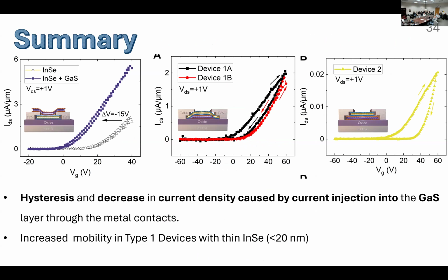So in summary, we have presented 3 different device configurations, and we have explored how the hysteresis and the current density are affected by the contact configuration. We have noted that direct contact with the gallium sulfide will lead to current injection that will take away current from the indium selenide, thereby reducing the maximum on current and inducing hysteresis. So we see that there is, again, this dependence on the thickness of the material.